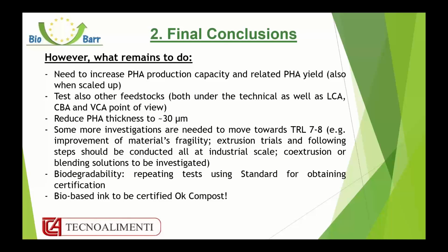Reduce as much as possible the PHA thickness, possibly, for example, to 30 micron, because currently we have used films which were more or less from 50 to 70, 80 micron. And the challenge is to reduce this thickness, avoiding the presence of pinholes and maintaining good mechanical and barrier properties.